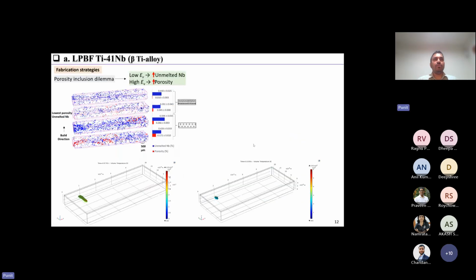So when we were printing this titanium 41 niobium beta titanium alloy, we wanted to essentially achieve in situ mixing, where we took titanium powder and niobium powder and mixed them and put them inside this LPBF processing unit, and we were trying to see if we can form an alloy by melting this mixture of the powder.